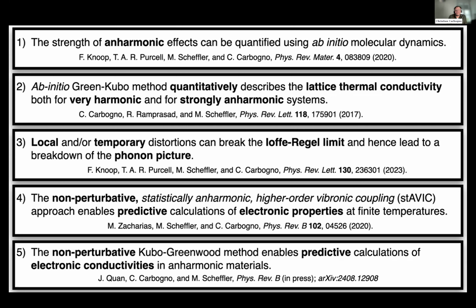Yes, in principle, yes. And sorry, it was not you missing it. It was me being a little bit fast on the last slides. In principle, you can calculate the thermal conductivity in metals for both nuclear and electronic parts. And for the electronic part, you can use exactly the Kubo-Greenwood method that I've showcased there. It works in the exact same fashion to calculate the contribution to the thermal conductivity from electrons. It needs just a little bit of adaptation in the actual formula, but it's conceptually and formally the same.